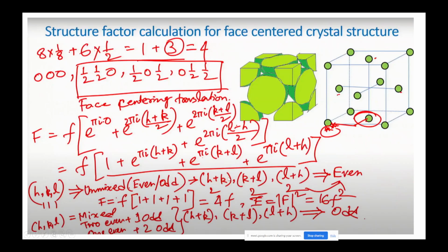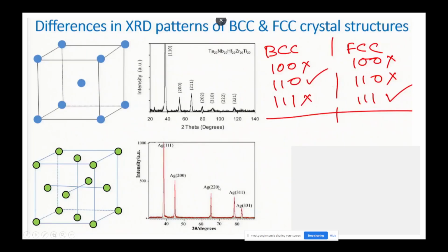Here you can see H plus K, K plus L, L plus H is even. So in your structure factor, when you calculate F, it will come to 4F. How will this 4F come? You have to put the values of H, K and L into this formula. And from where will you get H, K, L? From here. So this is unmixed, and H plus K, K plus L, L plus H is even. For BCC it's different. For FCC, when you see 111, H plus K is even, K plus L is also even, L plus H is also even. So this is for FCC.